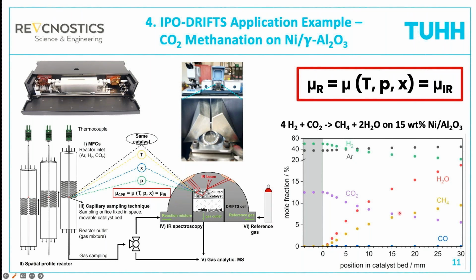And already this profile run takes a couple hours, because at every point you need to wait for the GC and for the IR spectrometer, so it takes a while, and then you have to exchange the catalyst to the diluent and do the same thing again. So between one point on the diluted catalyst and the same point on the pure diluent, we had a couple of hours time difference. And if you have a tiny drift in the spectrometer or in the catalyst performance or the reactor temperature, maybe there's a thermal drift, you will see this in the data. So this is not optimum. Best is you measure one point first on the diluted catalyst, and then you switch to the next cell and measure on the diluent alone, so that you get really the best possible correction of the gas phase.